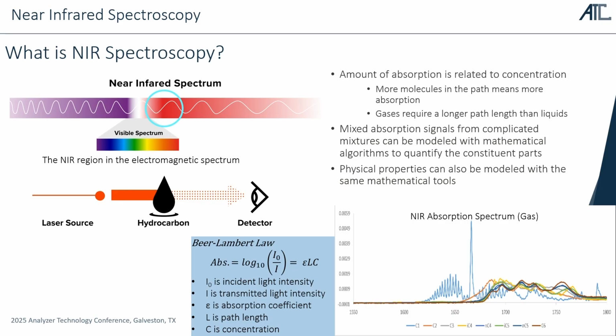Of course, when you have multiple components all together in a sample, your spectrum ends up with a whole bunch of individual absorption spectra lying on top of each other, so you can get some very complicated absorption spectra with complicated absorption features. So what we do to analyze that is model it with algorithms, known as chemometric modeling. And you can also model physical properties, because a lot of physical properties are a consequence of the composition of your sample. So those can be modeled too.